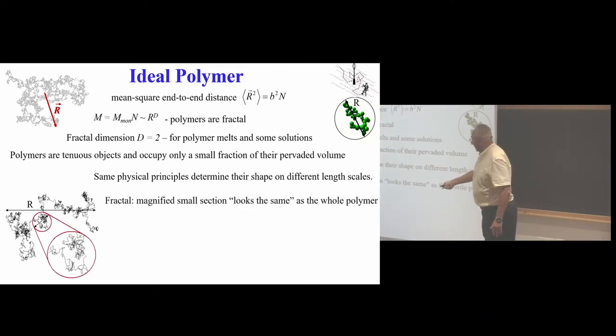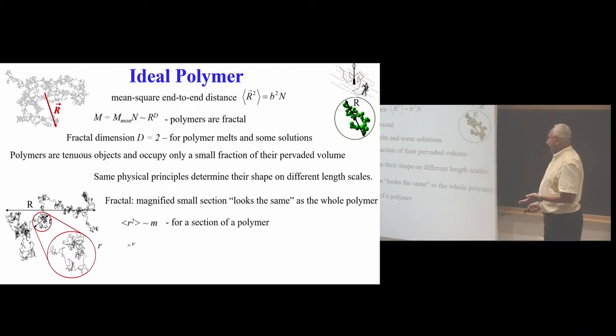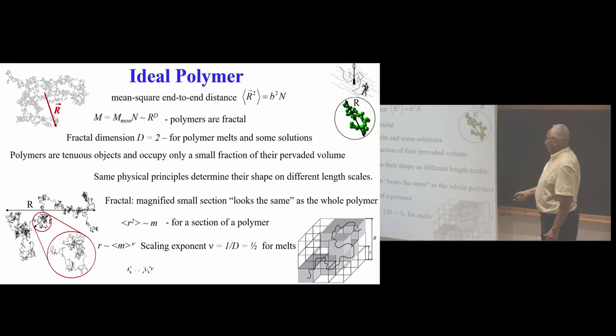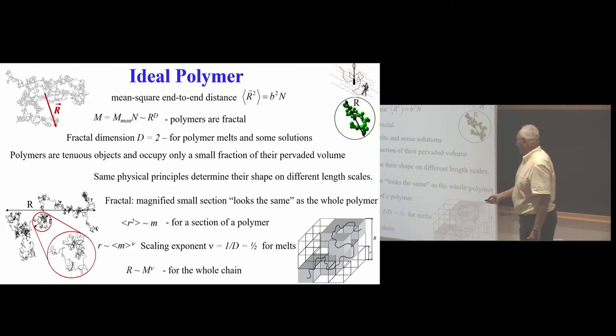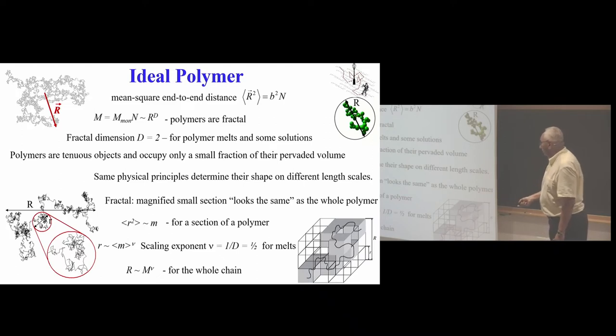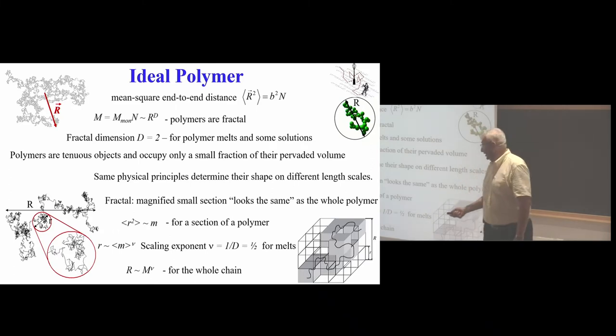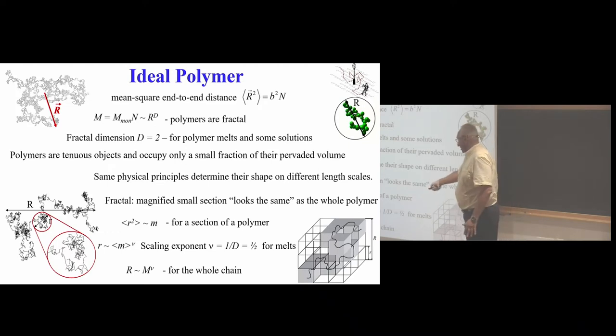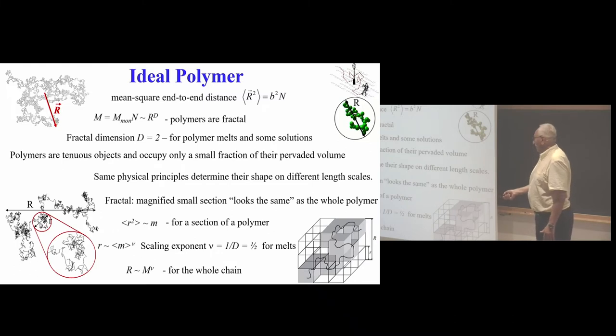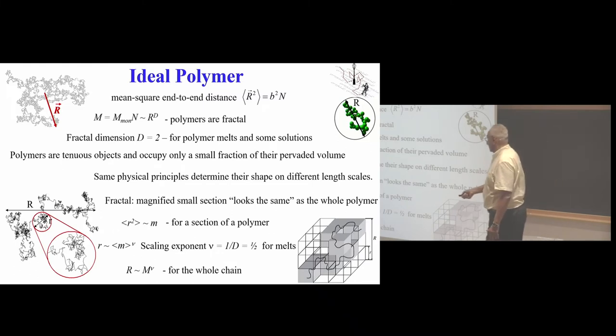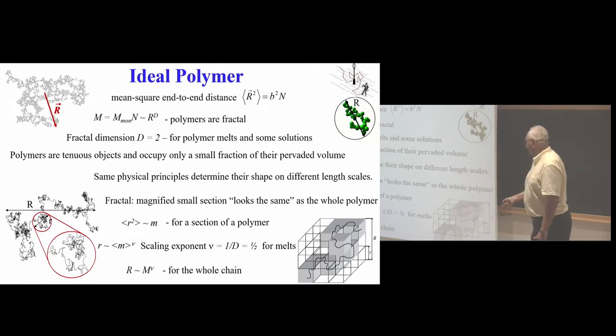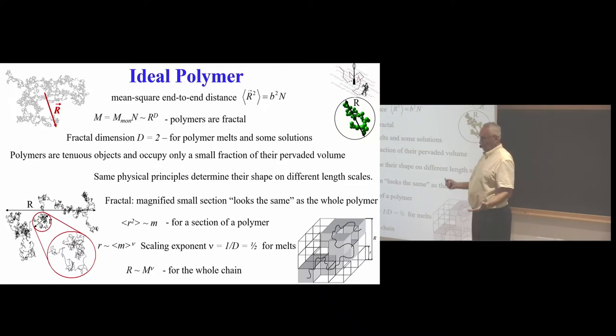Comparing fractal dimensionality D of a polymer with the space dimension three, there is plenty of other space around inside the polymer available for something else — lots of solvent or other polymers can fit in. It occupies a very small fraction of the volume. The reason it's fractal is that the same principle — in this case, completely uncorrelated random choice of direction — occurs on all different scales. That's why it's a self-similar object. We will use both capital D (fractal dimensionality) and nu (the reciprocal exponent: size proportional to mass to power nu, which is 1/2 for ideal chains).